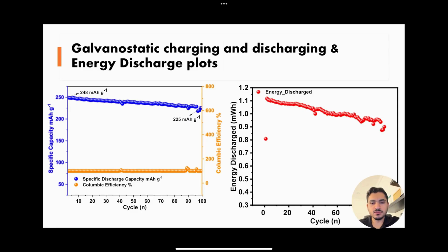Next is galvanostatic charging and discharging and energy discharge plots. On the left we have the GCD, where we activated the battery for about 2 cycles. Then we tested for the specific capacity, which returned 248 mAh per gram. After about 100 cycles, the specific capacity dropped to around 225 mAh per gram. The testing is still going, as you are going to see soon in the video. Throughout the cycles, we maintained an efficiency of 100%.